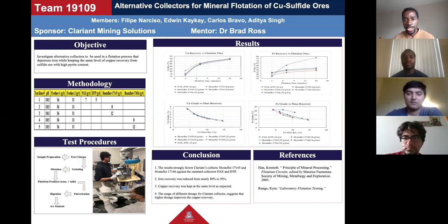To have a little bit more discussion on that, I'm going to pass to Aditya, who will continue with the development of the results. Thank you, Felipe. As Felipe was saying earlier, if we look at the copper recovery and flotation time graph, we realize that the copper recovery is nearly the same for all the collectors: the standard collectors, PAX and DTP, and the two new collectors in question. But we see a change when we look at the iron recovery graph. For the new collectors, the iron recovery reduces from 80% to 50% as compared to the original collectors. So we see a big decrease in the recovery of iron, which clearly shows that the new collectors are very efficient in suppressing pyrite while floating copper.